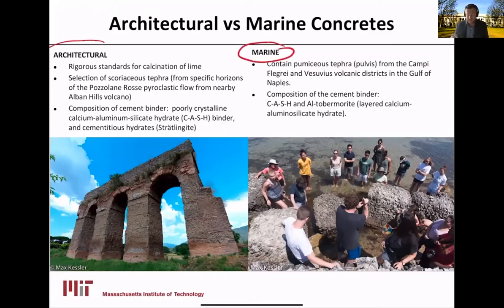Good. Returning to concretes, Roman concretes, architectural mortars, and marine mortars. What I didn't mention that's really important is that these blocks of Roman concrete actually set in water as well. So the key ingredient and the key reaction is hydration, not anymore CO2 uptake. And this means that these constructions would harden even under the surface of the sea, and that's really an important aspect that allowed the Romans to construct harbors and all the infrastructure in the Mediterranean.